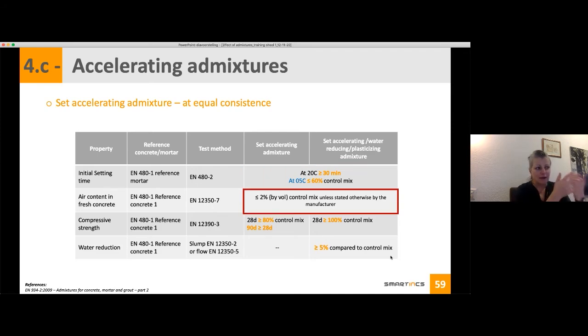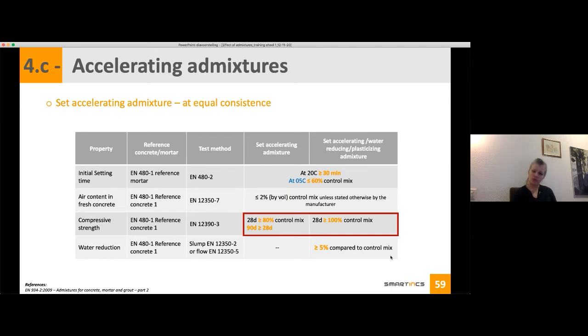If you look at the air content, nothing new here. You should not have more than 2% by volume compared to your control mix. And you also have some requirements relating to your strength, because it should accelerate, but sometimes that can be at the cost of your strength. You might think, oh, if it's faster, it would be better. But sometimes you have uncontrolled strength development, and your microstructure can be less well defined. So for a set accelerating admixture, at 28 days the strength should be more than 80% of your control mix, and at 90 days it should be higher than at 28 days. So it means that between 28 and 90 days, you should still have strength development.